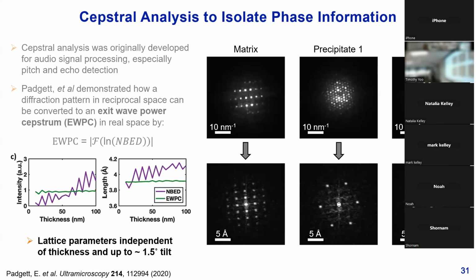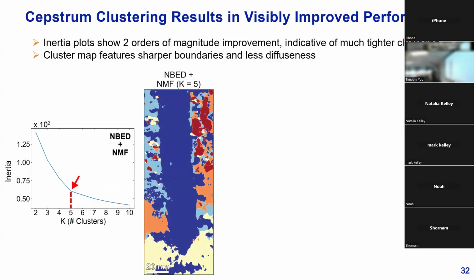From these examples of individual representative diffraction patterns of the three phases we saw so far, and the corresponding cepstral patterns, we can see that the patterns are nicely centrosymmetric in terms of intensity without necessarily sacrificing phase-related information. And so here's a recap of the initial clustering results again with the diffraction patterns.